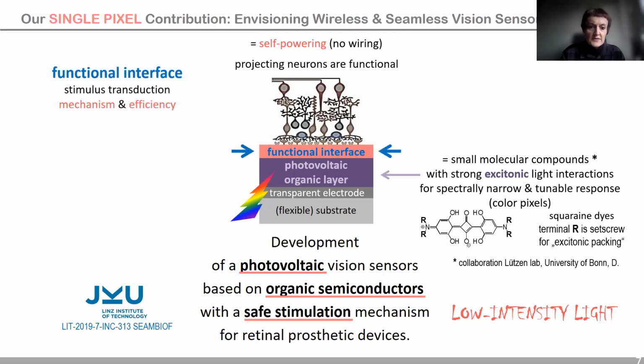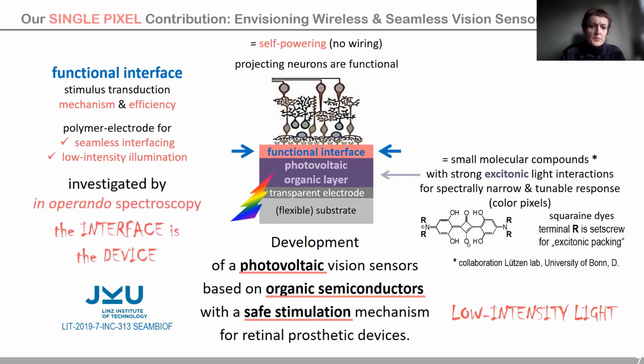And it is the functional interface that determines both the stimulus transduction mechanism and also the efficiency of the stimulus transduction. A polymer-based electrode is supposed to form a seamless junction between the photovoltaic layer and the living cells, and only a low light intensity should be required for the stimulus transduction. So to understand the transduction properties under operational conditions of the polymer electrode better, we use a special in operando spectroscopic technique. This spectroscopic tool studies the most critical part of the device, which is the solid-liquid interface.